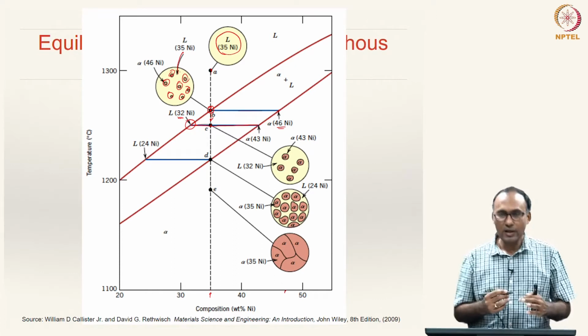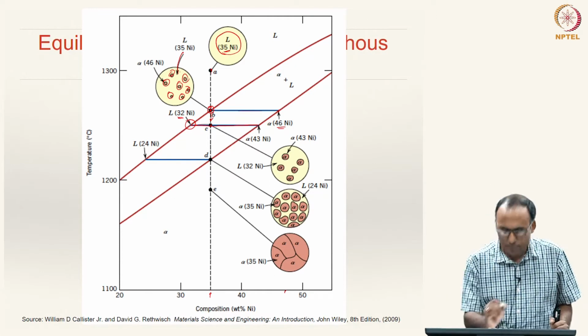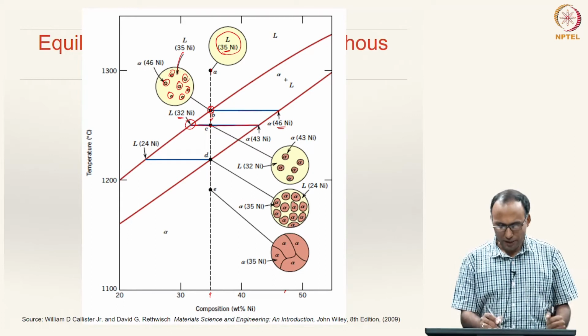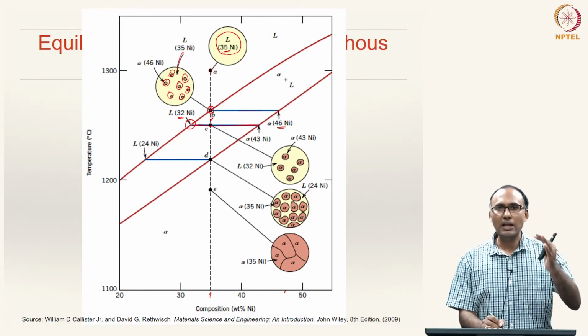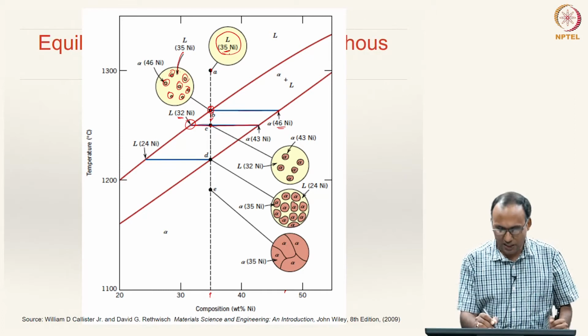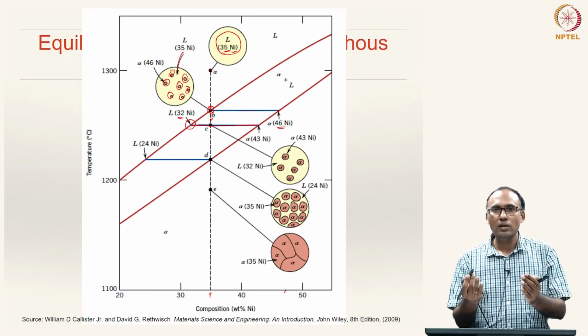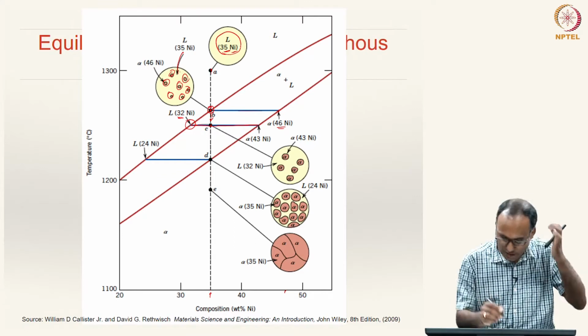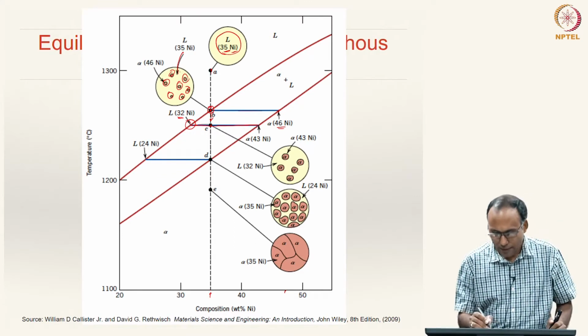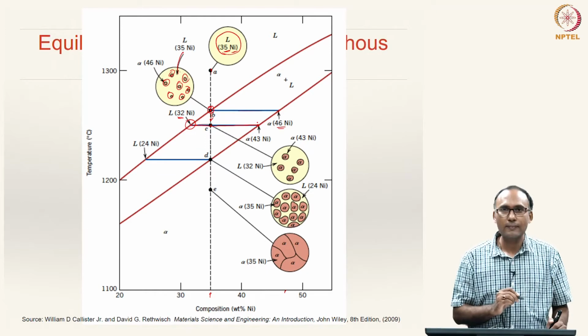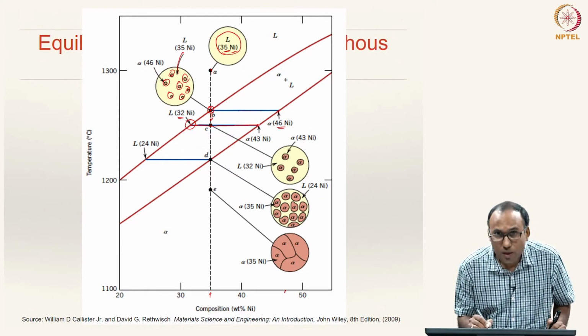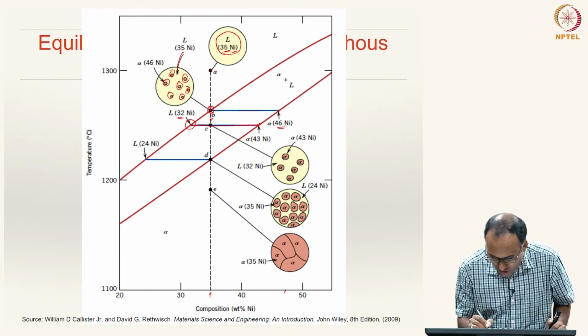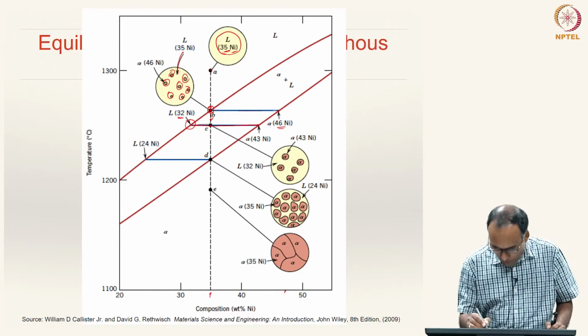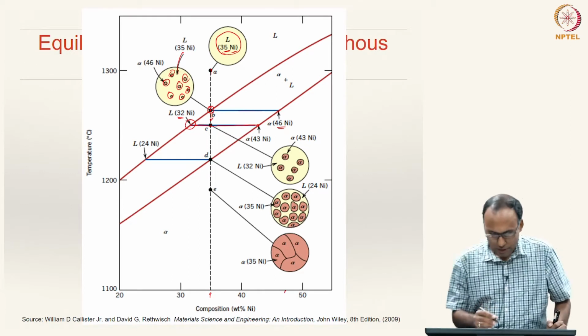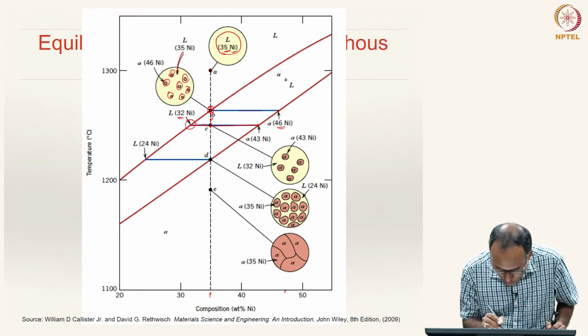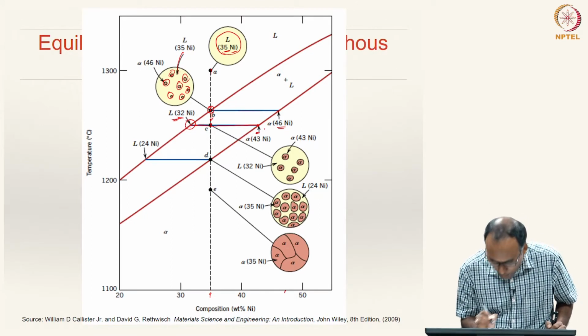That means, what is happening? Initially liquid was 35% nickel, and then by the time it reached here, the liquid became lean in nickel. That means nickel composition in liquid is reducing. So, it became 32% nickel, and the solid has also changed from 46 to 43% nickel, right. Now, you know what is the liquid composition and the solid composition.